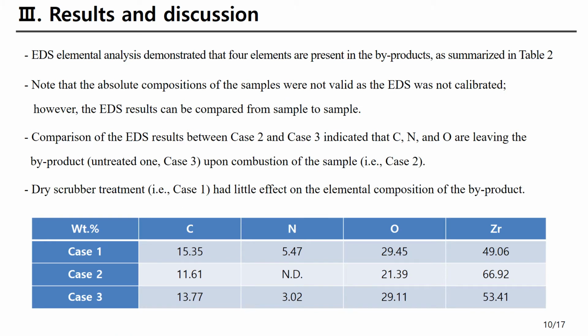EDS element analysis demonstrated that 4 elements are present in the byproduct, as summarized in Table 2. Note that the absolute composition of the sample was not valid, as the EDS was not calibrated. However, the EDS result can be compared from sample to sample. Comparison of the EDS result between case 2 and case 3 indicated that carbon, nitrogen, and oxygen are leaving the byproduct upon combustion of the sample. Dry scrubber treatment had little effect on the elemental composition of the byproducts.